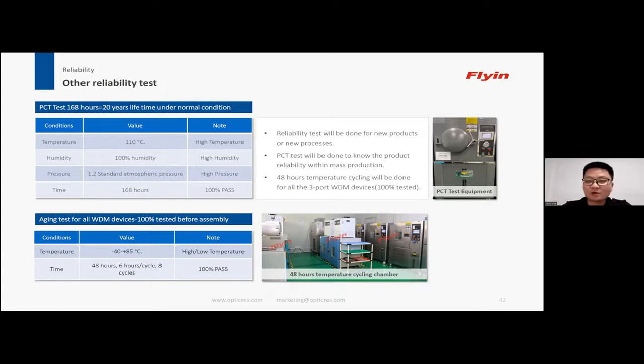And also for all the WDM single devices, we also need to have an aging test before we do the assembly. And the aging test is also a kind of temperature cycling. That means the temperature is from -40 to 85 degrees centigrade. And we also set it up for test with 48 hours, 6 hours a circle, and totally we have to take 8 circles. And for all the WDM devices, it needs to pass this test before we put them into the modules.